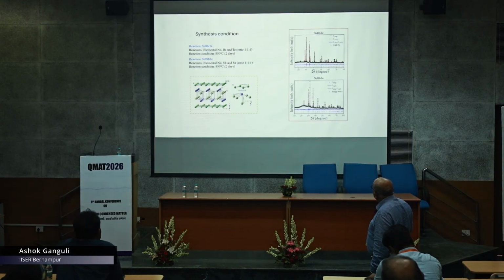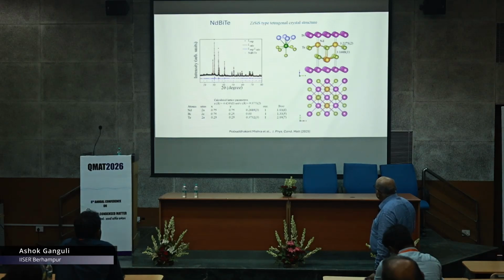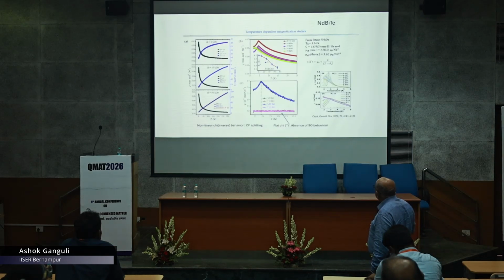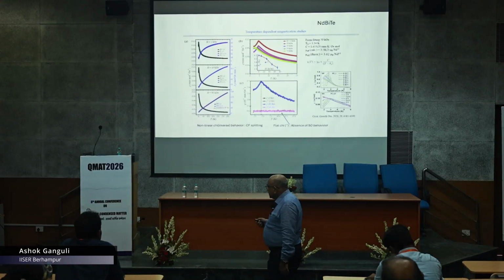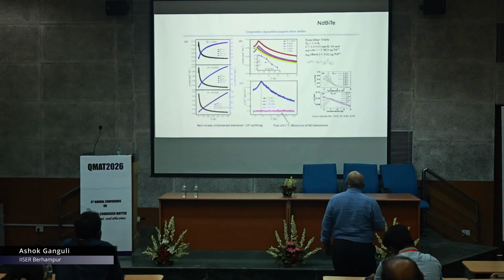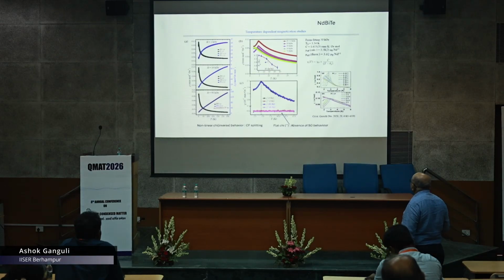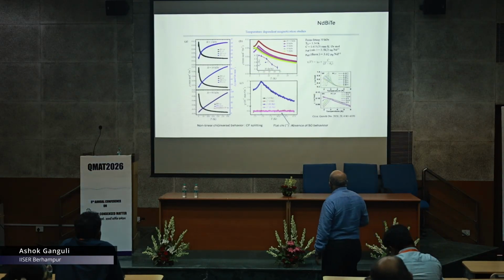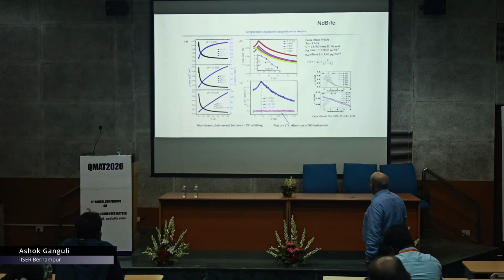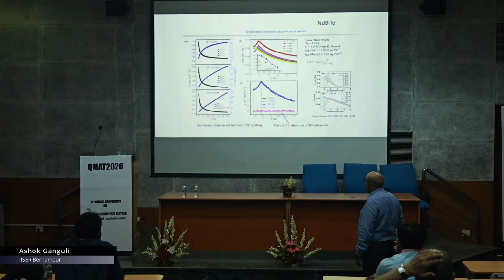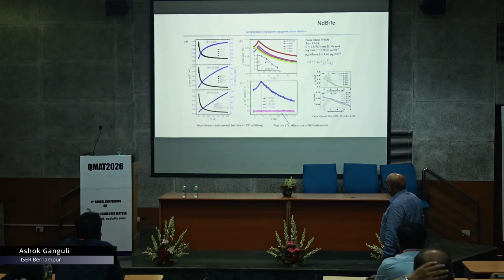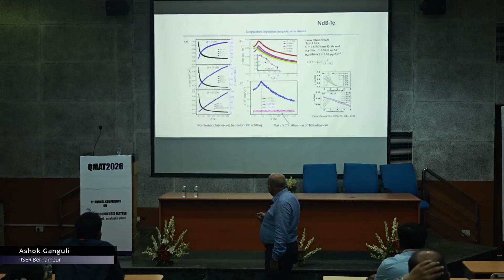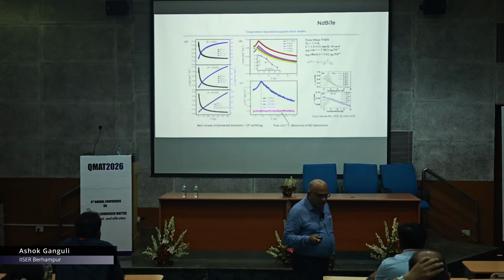So this is the structure, and these are the X-ray. This is more detailed if you want. This is the refinement. The structure is known to everybody, and these are planar nets of bismuth in this. These are the properties. The magnetism shows antiferromagnetic behavior. The Néel temperature is 3.3 Kelvin, and you can also see in the AC susceptibility that as you increase the frequency, your peak reduces, so we don't find this kind of spin glass behavior. And there is a nonlinear chi behavior which we ascribe to the crystal field splitting parameter.